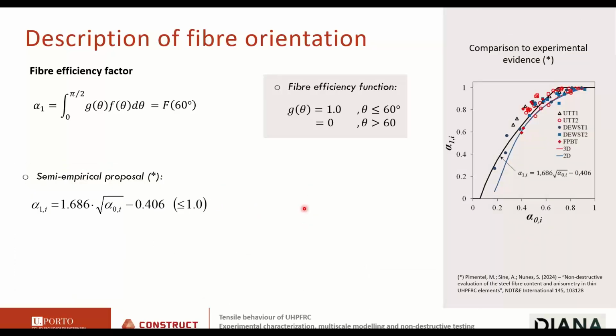Well, as we will see, under this assumption, we can determine the fiber efficiency factor from our image analysis of the polished specimens. And we have here the dots corresponding to the experimental values. So this plot relates the fiber efficiency with the fiber orientation. So what do we see? For fiber distributions with very large fiber orientation factors, the fiber efficiency factor is close or very near to 1.